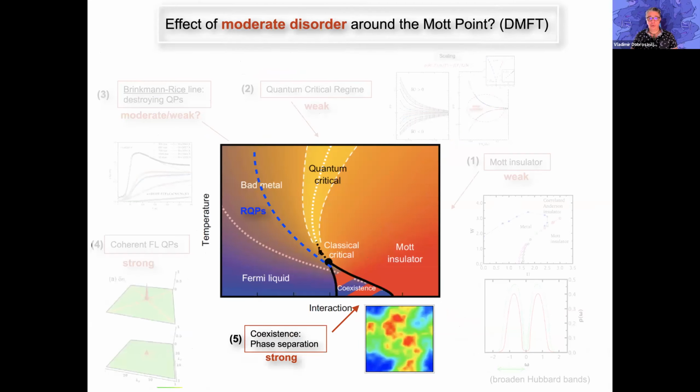Now, if we move even further, and from the Fermi liquid regime approach the transition itself at low temperature, what happens then? Well, we know that experimentally and theoretically, Mott systems at half filling feature a first order transition at very low temperatures. This is only about a few percent of the Fermi temperature, but it still can be seen in many experiments. And in particular in Mott organics, you see a first order transition up to about 25 Kelvin. In that case, the Fermi temperature is about 2000 Kelvin.